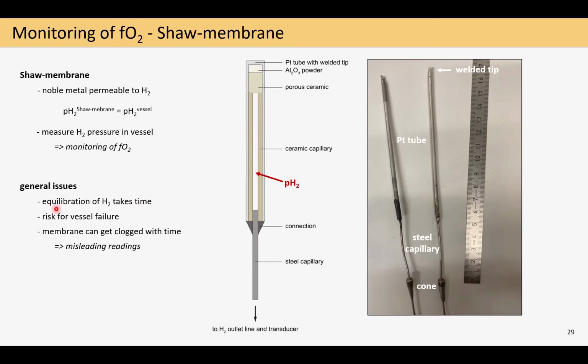Then they also pose a risk for vessel failure, since you have to imagine this small platinum tube, welded on top, is the only barrier or seal for the entire pressure inside of the vessel. So if this cracks, we will more or less empty the vessel in one go, and this has already happened from time to time in our lab.